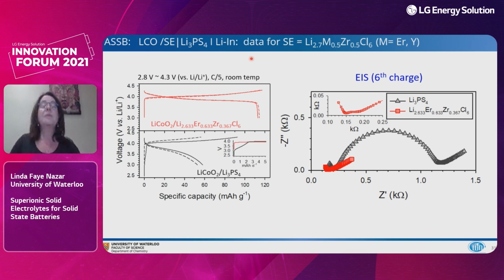So this just shows our first data that we reported, in this case it's for erbium, but the data is basically the same for yttrium. And it compares just a lithium cobalt oxide cell in which we've mixed it with a solid electrolyte, in this case Li3PS4, or in this case the halide. And then we're using Li3PS4 as a separator in these cells with a lithium indium anode. And so you can see immediately the effect of swapping out the solid electrolyte in the cathode from Li3PS4 to the halide is really quite dramatic in terms of the capacity that we can sustain and also the cycling that we can sustain.